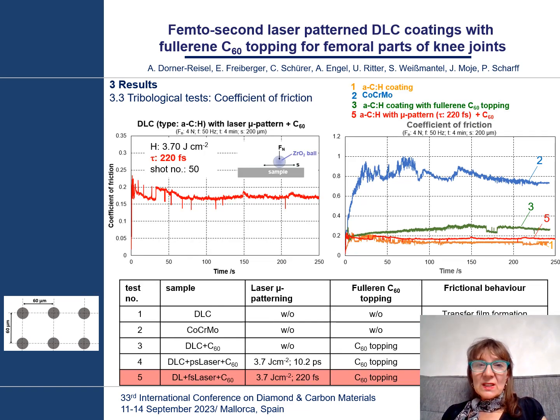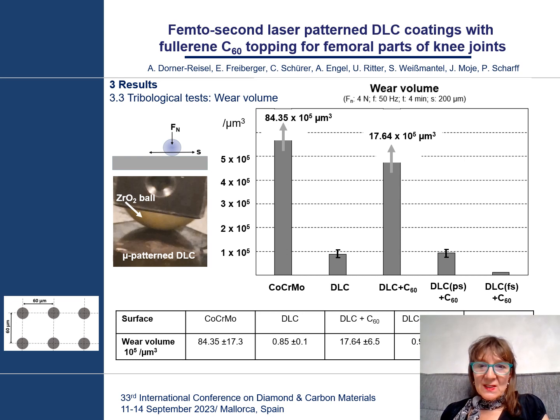Femtosecond laser dimpled diamond-like carbon with C60 topping shows a minorly increased coefficient of friction in comparison to picosecond laser dimpled DLC with C60 topping and diamond-like carbon without dimples and C60 topping. It was really a surprise to see that diamond-like carbon with femtosecond laser patterning and C60 topping showed the lowest wear volume, which means the best wear resistance, even better than diamond-like carbon without C60 topping and without laser patterning.